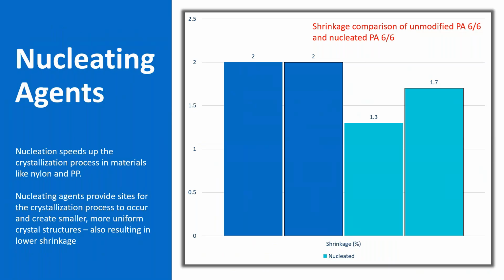So things to keep in mind, we can add specific nucleating agents on purpose to get it to cycle faster and more uniformly, but also some things might have that effect even without it being distinctly a nucleating agent. So keep that in mind. It's most common in nylon and polypropylene, even more common in something like a nylon 6,6, because nylon 6,6 crystallizes faster already compared to a 6. And so adding the nucleating agent makes it crystallize even faster. Very common in polypropylene. A lot of the commodity grades that we sell, you're going to see that they come with a nucleating agent already.